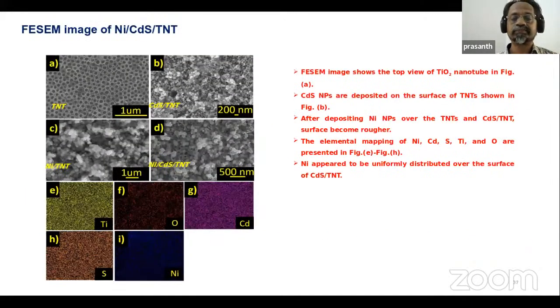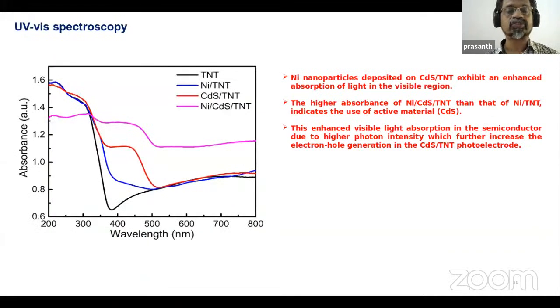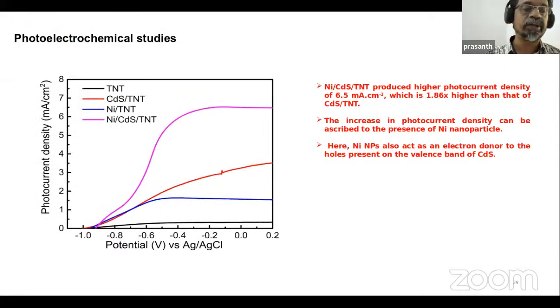So in that case, again, you have to optimize the structure. When you are making a proper deposition of the nickel nanoparticle, that can harvest more light through the plasmonic effect, and it is also acting as a protective layer against CdS degradation. That is an additional advantage. You can see how the light harvesting property of the electrode is increasing by including the nickel nanoparticle into the system. So that means you can generate more photocurrent.